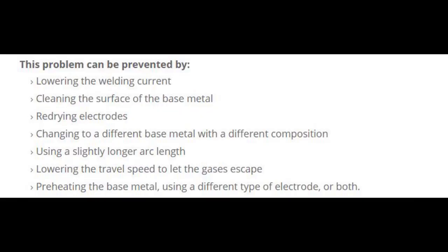This problem can be prevented by: lowering the welding current, cleaning the surface of the base metal, redrying electrodes, changing to a different base metal with a different composition, using a slightly longer arc length, lowering the travel speed to let the gases escape, preheating the base metal, using a different type of electrode, or both.